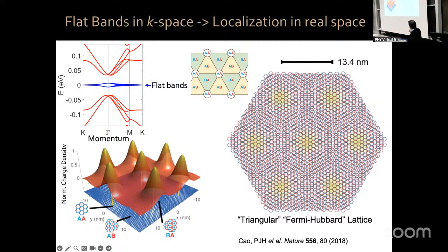I use quotes many times here because, first of all, it's not really triangular—this is actually a honeycomb Moiré lattice, since the AB and BA regions are not identical. It's also not a standard Fermi-Hubbard lattice, because the electronic structure of magic angle twisted bilayer graphene has certain topological properties that prevent a direct mapping to the usual vanilla Fermi-Hubbard lattice used in cold atom experiments. So it's an analog, but quite different in practice.